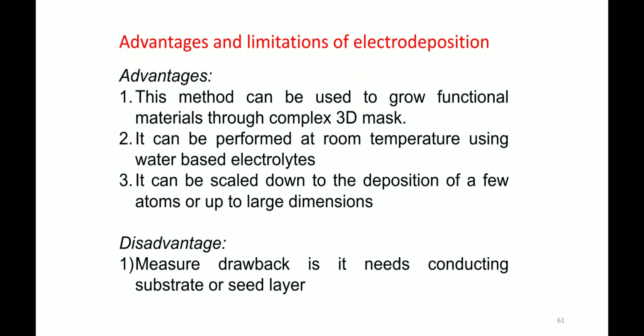So thickness can also be tuned very simply, you can just minimize your potential, and if you keep a very low time of deposition, then you can get an ultra thin film. The major drawback is it needs a conducting substrate or seed layer. If the substrate is not conducting, at least there should be some seed layer of conducting material. As long as the circuit is completed, the electric current will flow, and only then is there a deposition of the material. Otherwise, if you want to deposit on semiconductor or insulating materials, then substrates of insulating material or semiconducting material are not that useful.